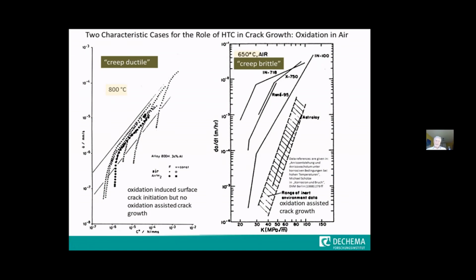Now things can be quite different if we move to so-called creep brittle materials, which means materials that have a much higher creep strength. Again, we have the inert environment here, and you see there are some materials which are quite sensitive to the environment with regards to creep crack growth. Especially this one here, the 716 or 718, shows a strong acceleration of the crack growth rate in the presence of oxygen. Since these have a high creep strength, you can use the K parameter instead of the C star parameter as the fracture mechanics parameter. Now this was for air.